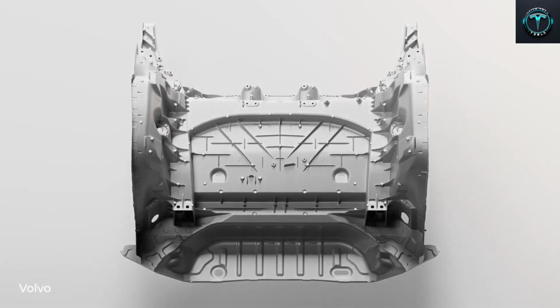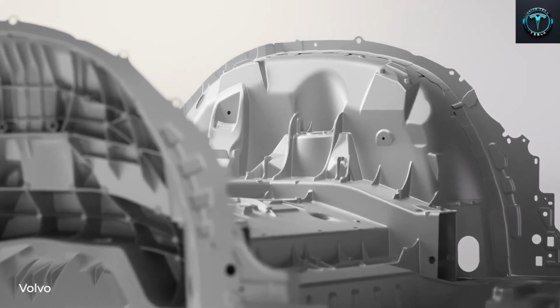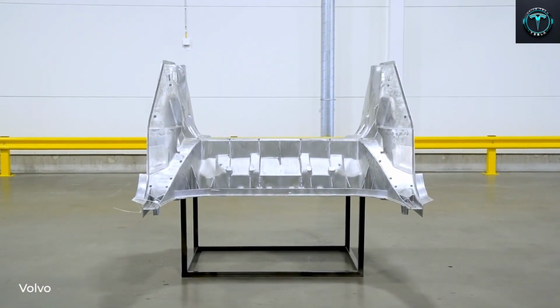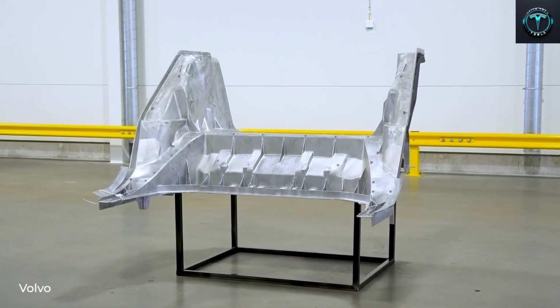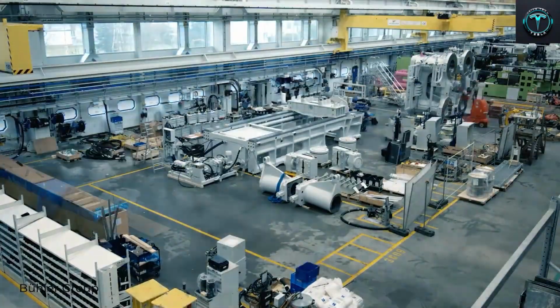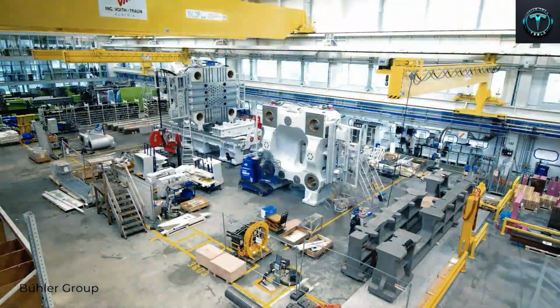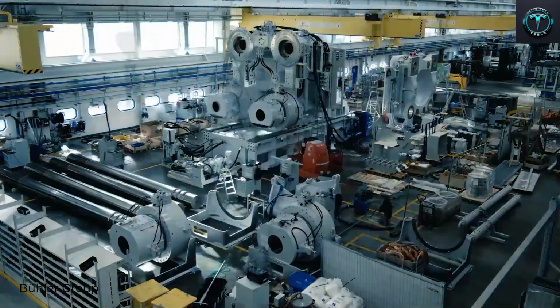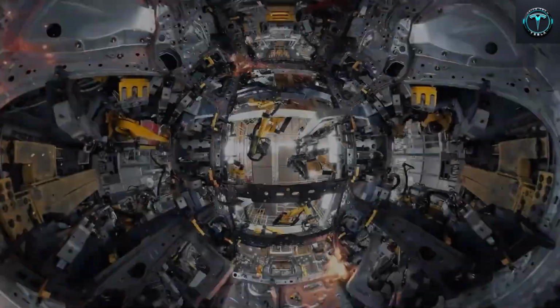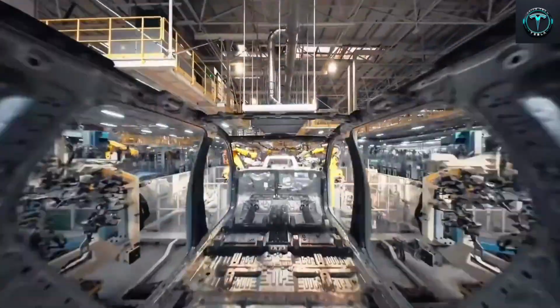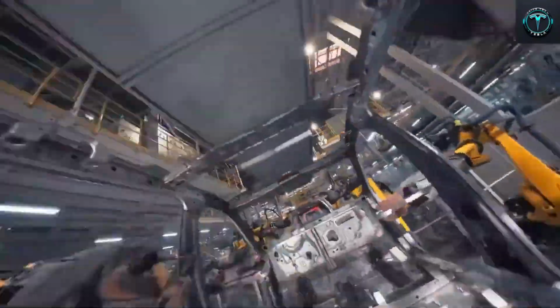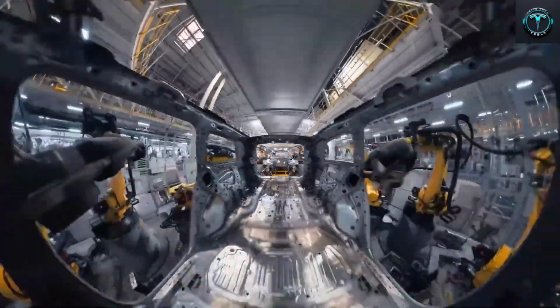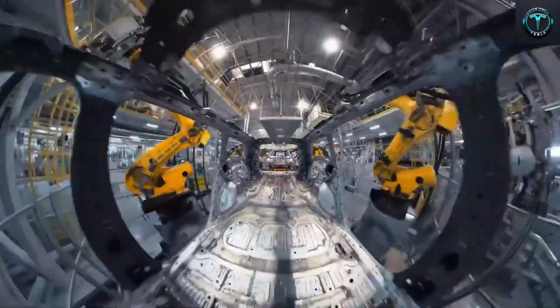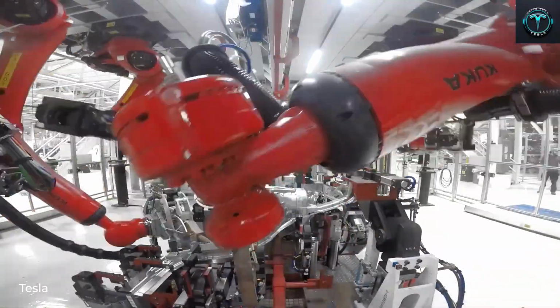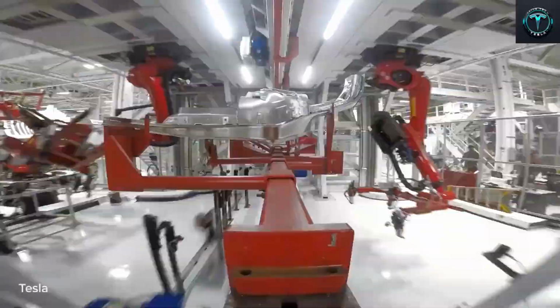Tesla runs this on a dual furnace setup, one powered by natural gas that handles the initial melt, and a second electrically heated furnace that maintains the metal at that ideal holding temperature. But heat alone isn't enough. The space inside that holding furnace gets filled with nitrogen gas to stop the molten aluminum from reacting with oxygen and forming unwanted oxide buildup, while also keeping conditions stable. To purify the alloy even further, Tesla uses argon gas, a rotary degassing process, and a silicon carbide filter to strip out dissolved gases and catch particles larger than 25 microns. Only after all of that does the aluminum move on to the next stage, prepping the mold.